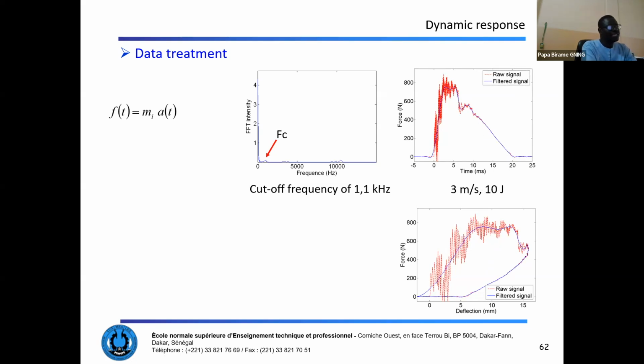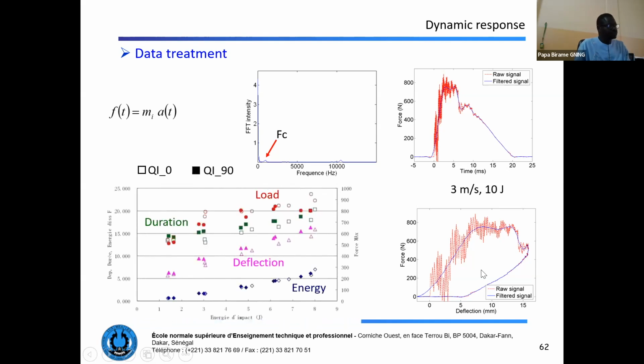So when the damage is created, we see irregular evolution of force depending on time, and the loading unloading curve shows important dissipated energy. Here is plotted the evolution of the energy dissipated as a function of the impact energy. We see that it's increasing.